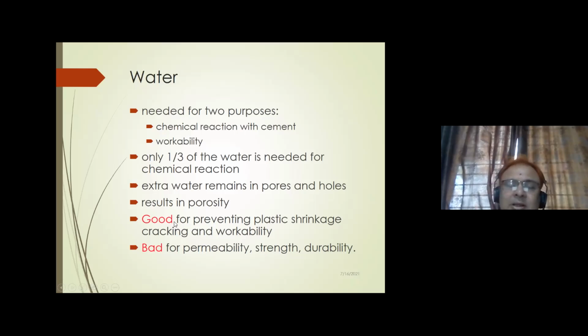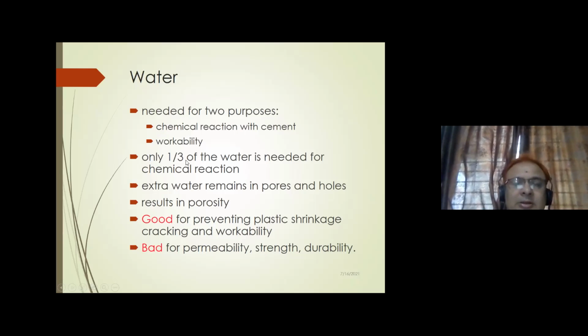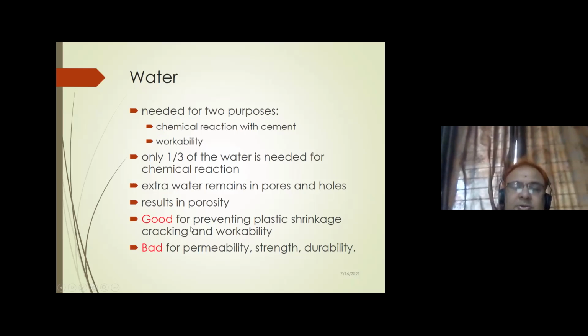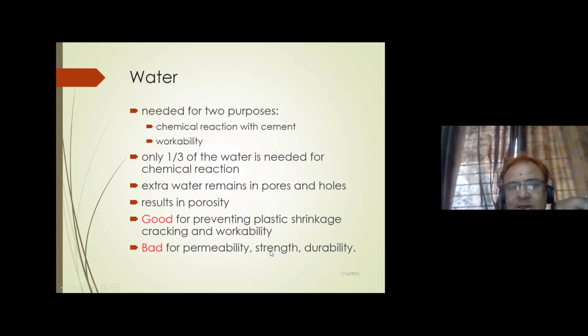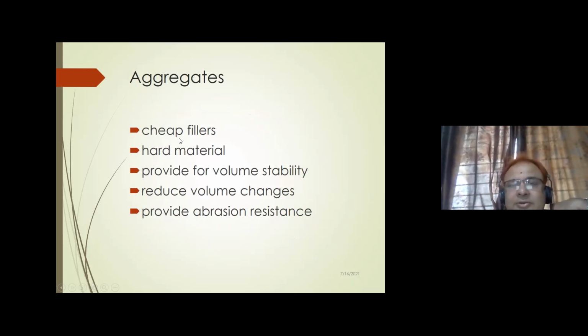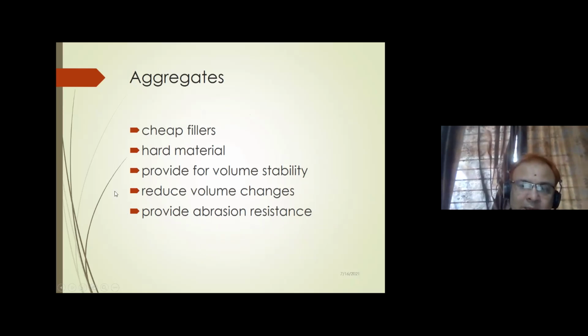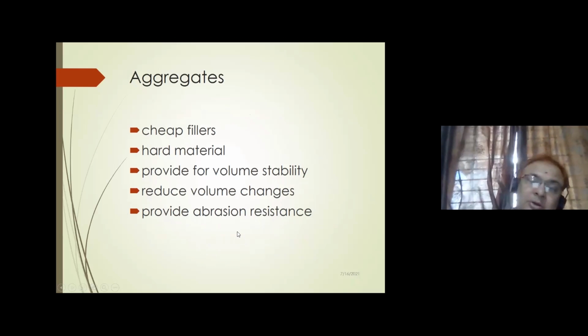Excess water, if we go for more water than the design, is good for preventing plastic shrinkage cracking and for workability, but bad for permeability, strength and durability. We are not getting enough strength if water is in excess. Aggregate is the chief filler, a hard material, providing volume stability, reducing volume changes and providing abrasion resistance in the case of pavement and roads or flooring of a godown also.